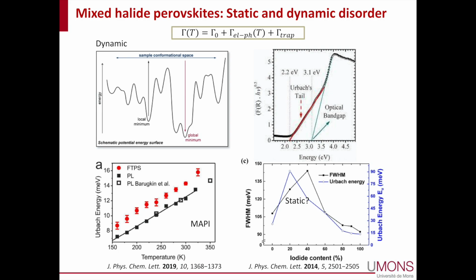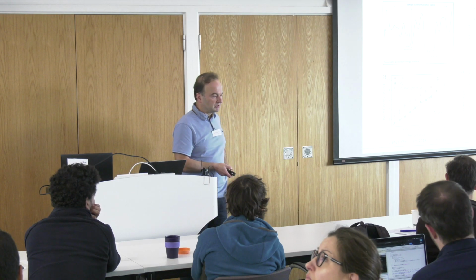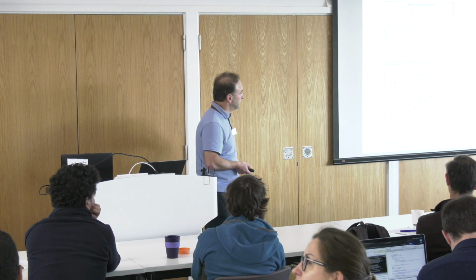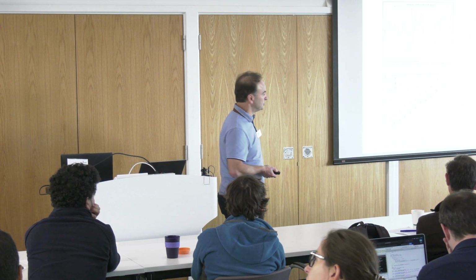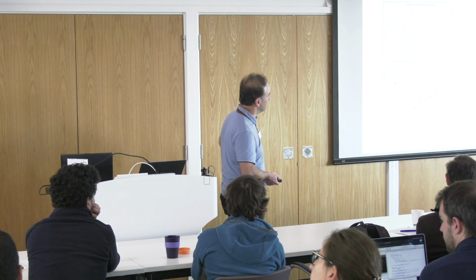What is really fascinating with those materials is that if you can do temperature-dependent measurements of the Urbach energy, for instance, as shown here, it seems that it goes down all the way to smaller and smaller values as you decrease the temperature. So it seems to indicate that the homogeneous contribution, the dynamic contribution, is really dominant.